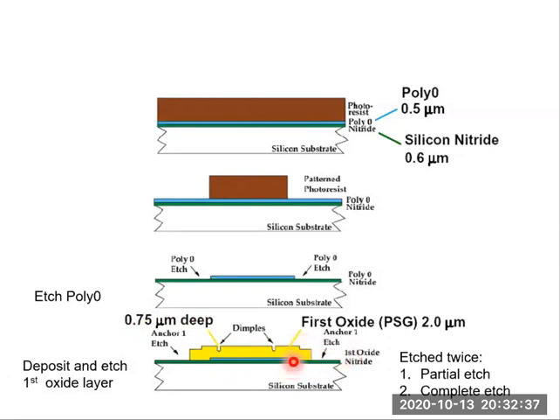Right? This oxide layer itself is 2 micron. So this is a partial etch. The second etch is this anchor 1 etch. Right? It's a complete etch. The PSG layer is completely etched down to the nitride layer. So 2 etches, one is a partial etch, one is a complete etch. Later we will know the purpose of fabricating these dimples.